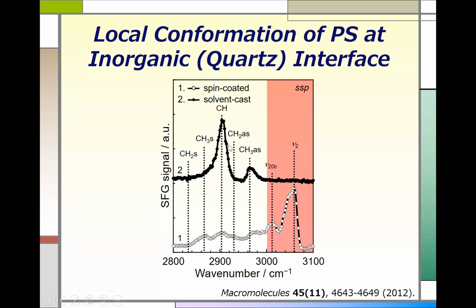Actually, this polystyrene film was sandwiched between two quartz substrates. So we have only the interface of polystyrene with quartz. And then we have been looking at the CH vibration, I mean, just polystyrene information. And you see that this shape is not the same as this one. So what it means is that polystyrene has completely different conformation at the quartz substrate if we apply two different methods.